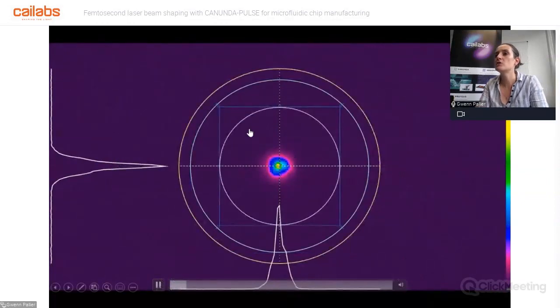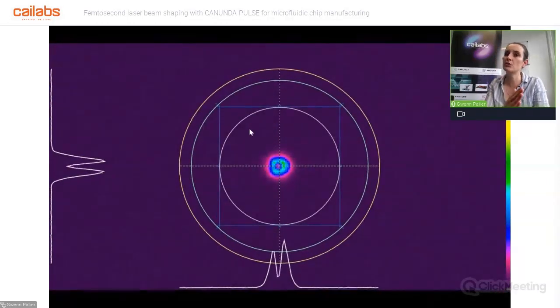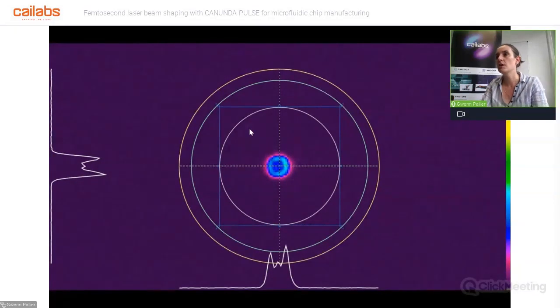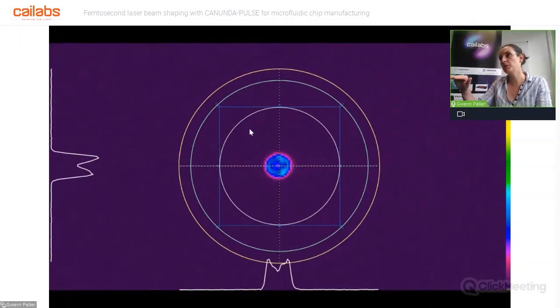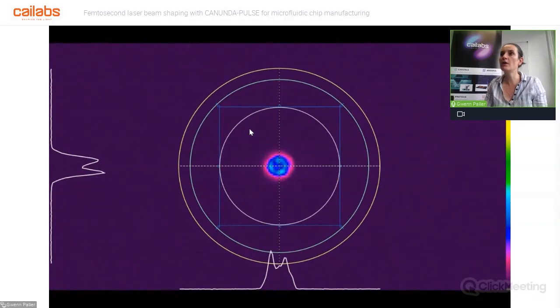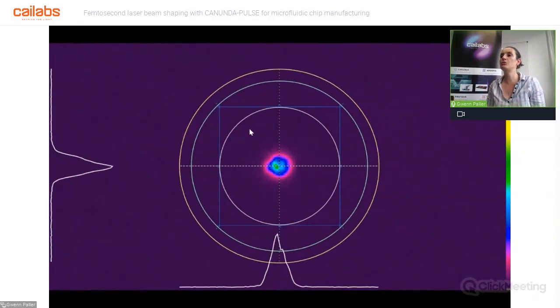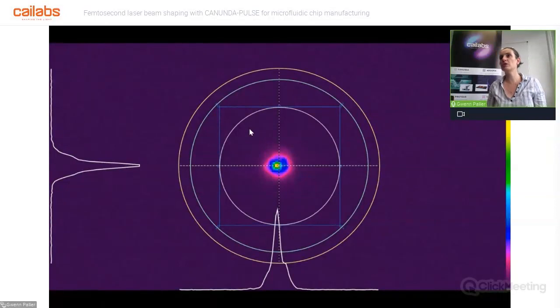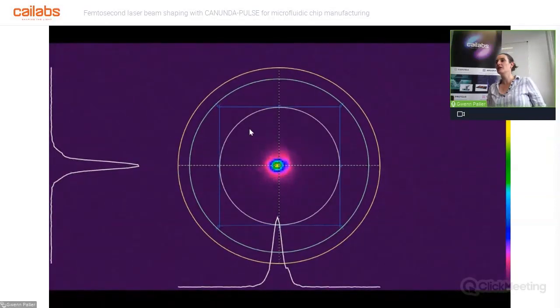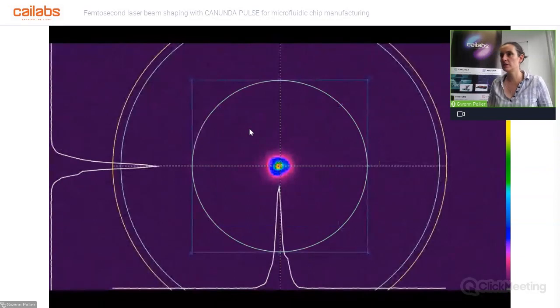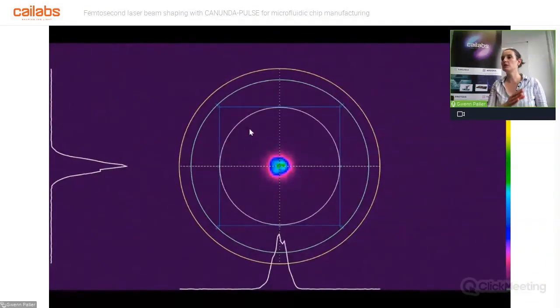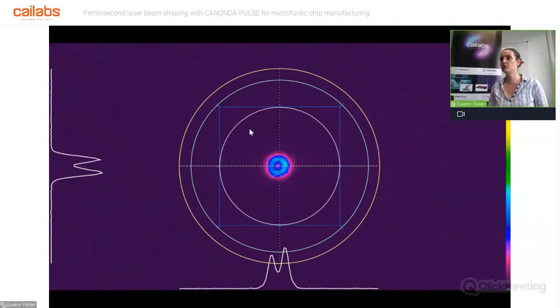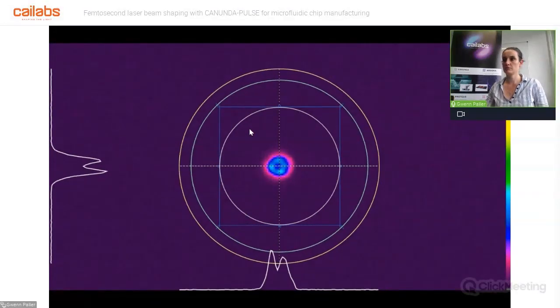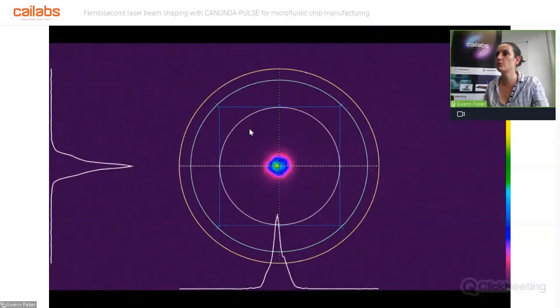And here you can see actually how the shape is behaving when you are scanning over the propagation. So you have this U shape in the middle of the propagation, and you have a certain depth of field over which you preserve this U shape. And after that, you don't have something which is so weird that you cannot do any process or anything. You have kind of a peak shaped. It's getting again over the depth of field. So you go from the peak shape to the U shape, which is preserved, and then you get back to the peak shape just when you get further from the best focus.